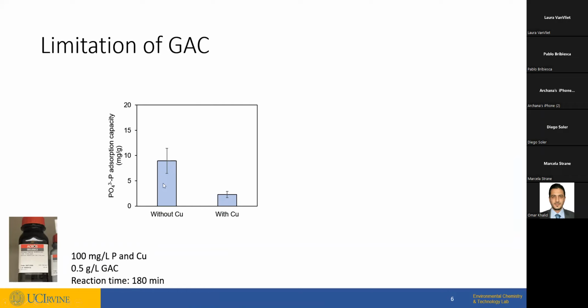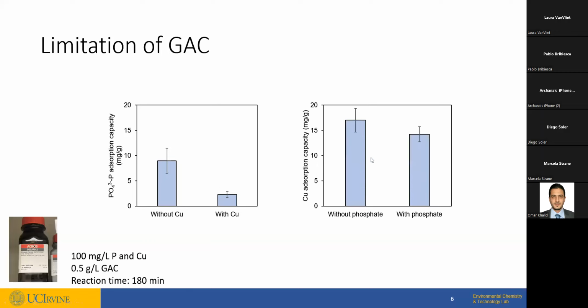This is the data for phosphate removal capacity of GAC. You see that when phosphate is just by itself, it barely gets to 10 milligram per gram removal. And when the second contaminant is present, the capacity of GAC goes down. Similarly, when we measure copper by itself, it's about 17 milligram per gram in terms of the adsorption capacity. But when phosphate is also present in the system, it's below 15.